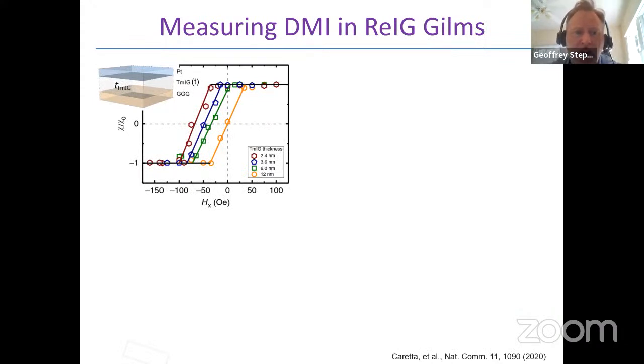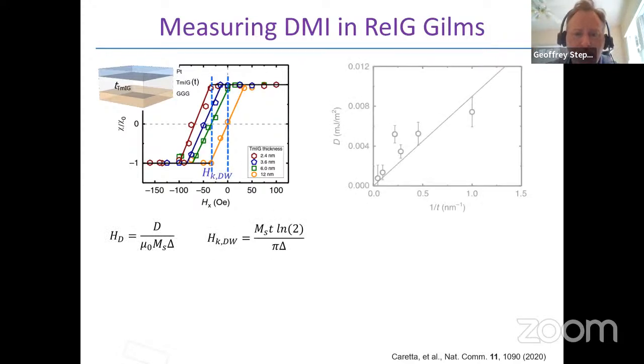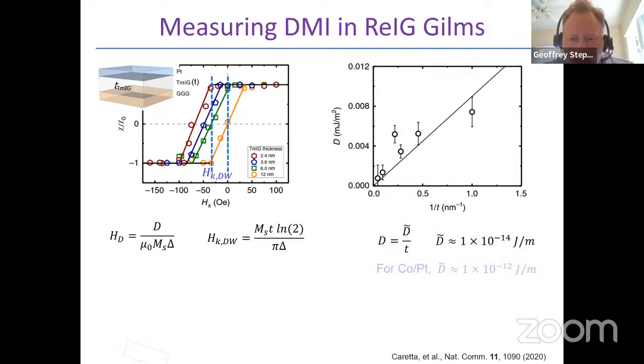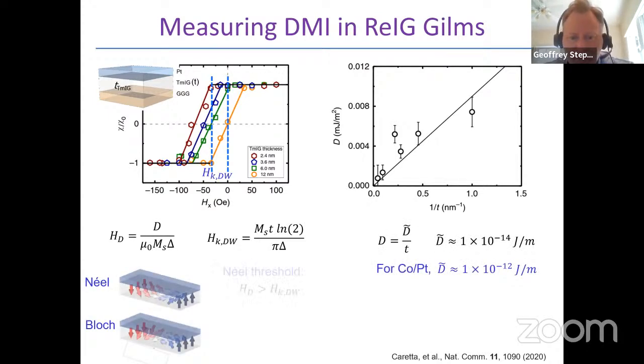And for thulium iron garnet, when we look at the DMI, which in this figure you can take as the zero crossing of these data, so that's the field at which the domain wall is blocked, we find that the magnitude of the DMI decreases as the thickness increases. And so that points to an interfacial origin of the DMI, so that D scales as 1 over thickness. And let me skip through the equations here.